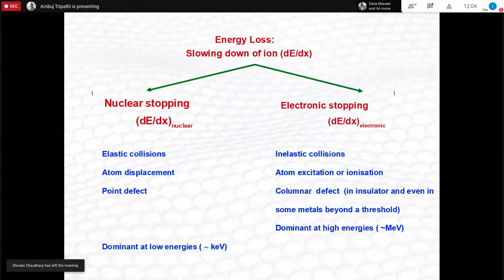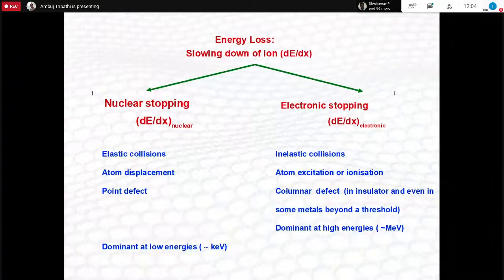So elastic, what happens is a simple momentum transfer, and this leads to atom displacement, and the defects will mostly be point defects. And mostly we talk about lower energies. Lower energies means of the order of a few tens to hundreds of keV, where elastic collisions will dominate. And as you increase the energy, if you go to the higher energy side, which is on this right one, you will see electronic stopping.